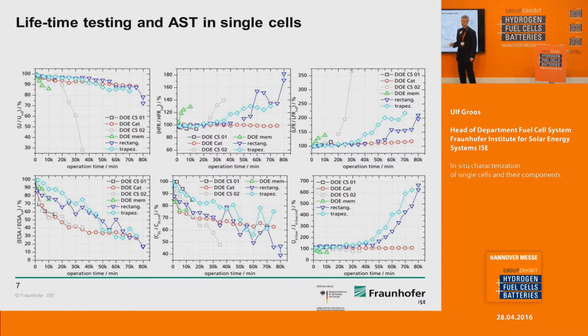So here we had a rectangular load profile which we applied to the cell, and a trapezoid load profile. We did a lot of cycles, so what you see here is that we performed this AST test up to 80,000 cycles. And we compared it in one setup, so every AST protocol was performed within the same test bench and the same test cell. So we had a very good comparison of the effects of different load profiles, different long-term test protocols.